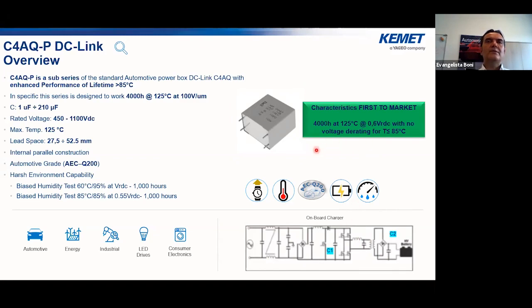One important point of this series is that it is not first to market, but there are some characteristics that are first to market. In this case, this series can work 4,000 hours at 125 degrees without any derating at lower voltages. So there is no derating or decrease in the voltage at lower temperature versus the standard C4AQ series. And this is a really great achievement of the development of this KEMET series.